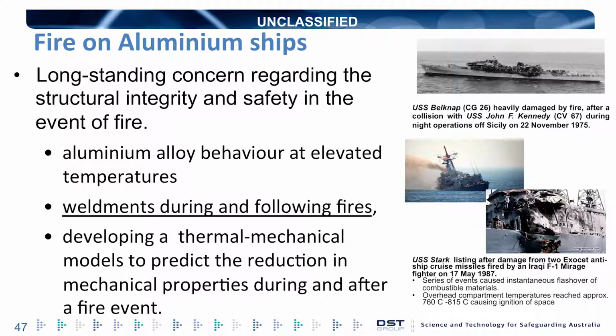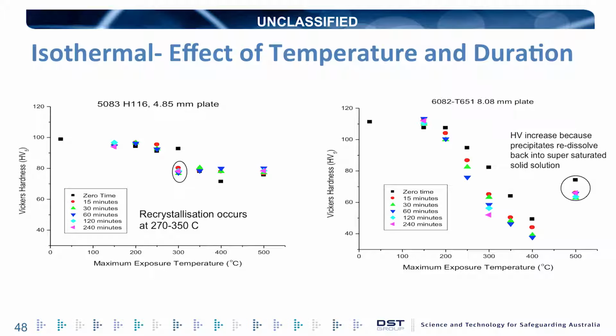Fire is another problem in aluminium structures again, and the behaviour of weldments during fires. There was a lot of fire on ships in the Falklands, etc., but we have smaller fires, and so how good are they for welded structures? So these two graphs show hardness up the side and maximum exposure temperature along the bottom. So 0 degrees here up to 500 degrees. And the different colours are exposure to various times.